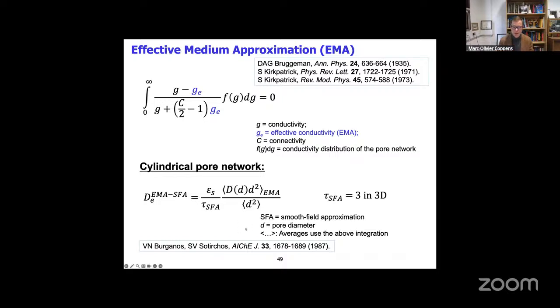this theory breaks down. Now, what Burganos and Sotirchos did, and I think this is brilliant work and dates from the 1980s, what he showed elegantly is that if you combine EMA with a so-called smooth field approximation, this means that you assume an effective theory where you replace the connected space by some effective mean field model for the pore space. And so that means that you can even calculate that the tortuosity in that effective space would just be 3 in 3D. In 2D models, it would just be 2. Then you can use the EMA on that in combination with the smooth field approximation. That gives you an extremely good representation.